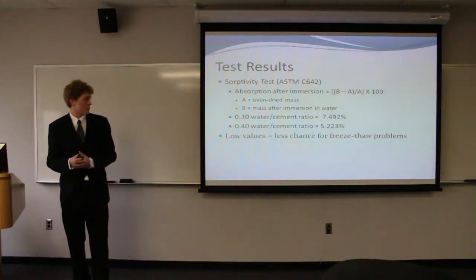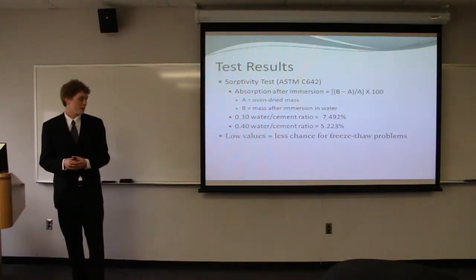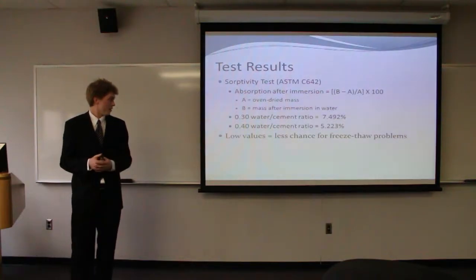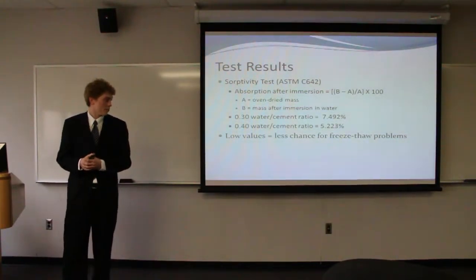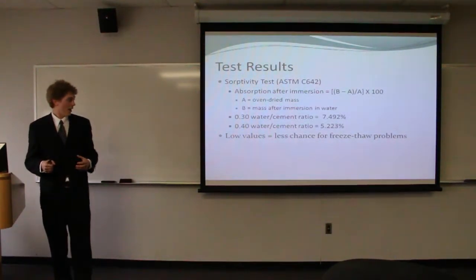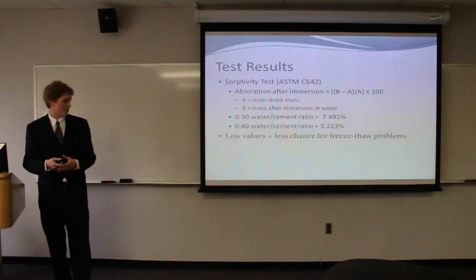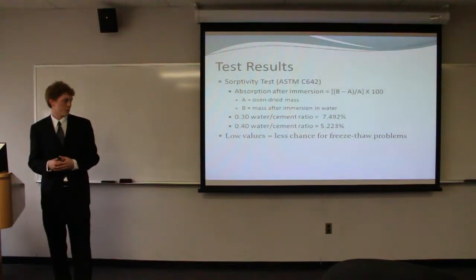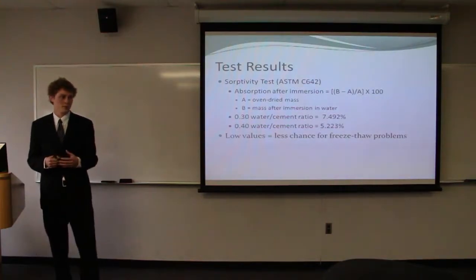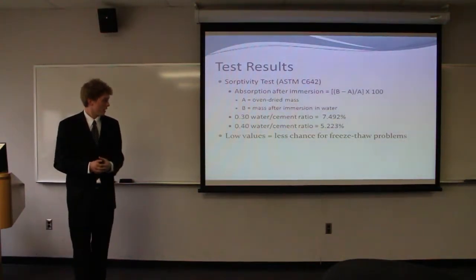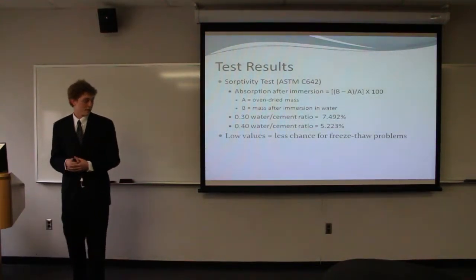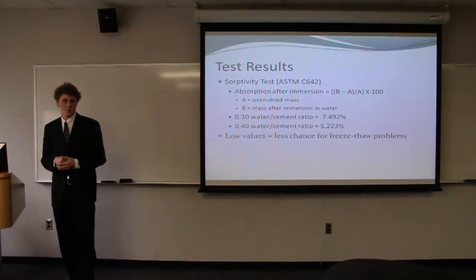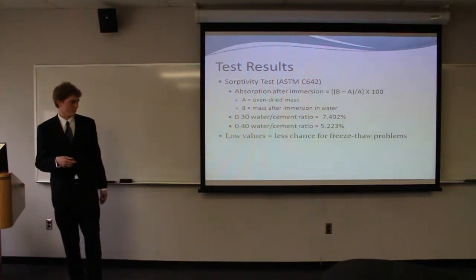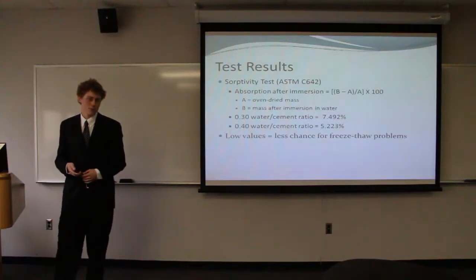We also performed a sorptivity test on our pervious concrete. For the .30 water cement ratio, we got a 7.492% absorption rate, and for the .40 water cement ratio, we got a 5.223% absorption rate. And these are values that are rather low for pervious concrete, which is a good thing because then there's less chance for freeze-thaw problems to occur with the pervious concrete.